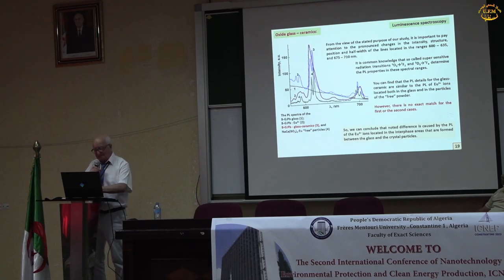You can find that the PL details for the glass ceramics are similar to the photoluminescence of europium 3+ ions located both in the glass and in the particle of the free powder. However, there is no exact match for the first and the second case. So we can conclude the noted difference is caused by the photoluminescence of the europium 3+ ions located in the interface area that are formed between the glass and the crystal particles.